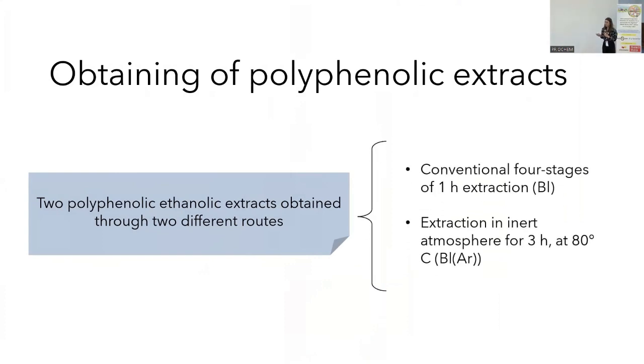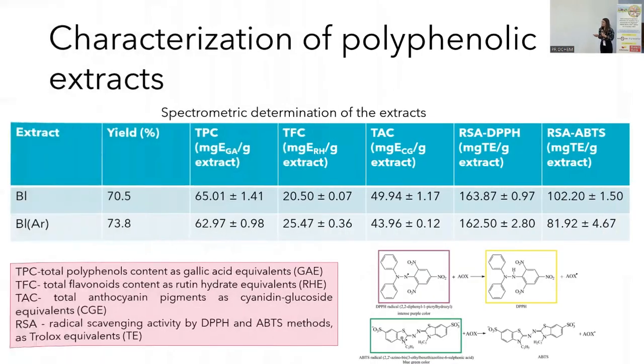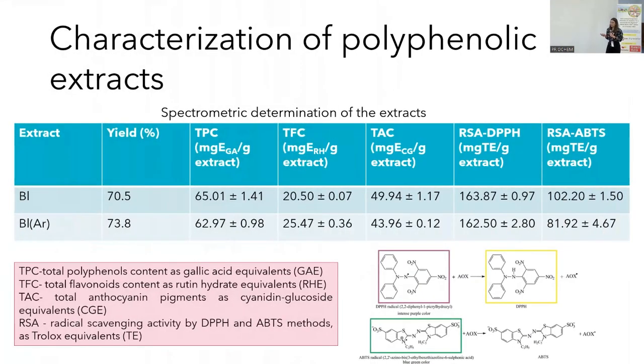The first one in a conventional four stages of 1 hour each extraction at reflux with solvent replacement, and another one in inert atmosphere in 1 stage of 3 hours at the same temperature as the first. The chemical profiles of the polyphenolic extracts were assigned using spectrophotometric methods and HPLC-PDA chromatography. The spectrophotometric methods helped us to reveal the total contents of polyphenols, flavonoids, and anthocyanins, as well as the radical scavenging activity correlated with the antioxidant properties.